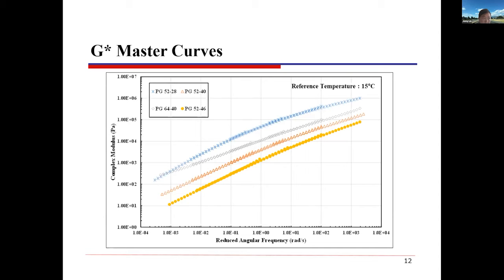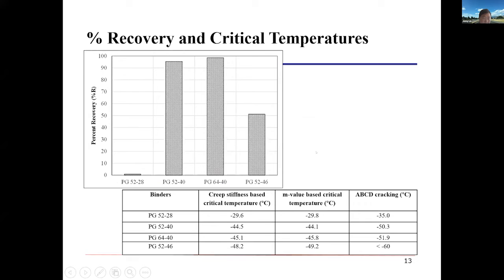So here, this is the G-star master curve of the studied HPABs at the PAV aged state, as well as the unmodified binder PG52-28 at a reference temperature of 15 degrees Celsius. The unmodified binder PG52-28 showed the highest G-star. In other words, the unmodified binder was the most stiff. It was generally believed that a softer asphalt binder at higher frequencies or intermediate temperatures would perform well in terms of fatigue cracking resistance.